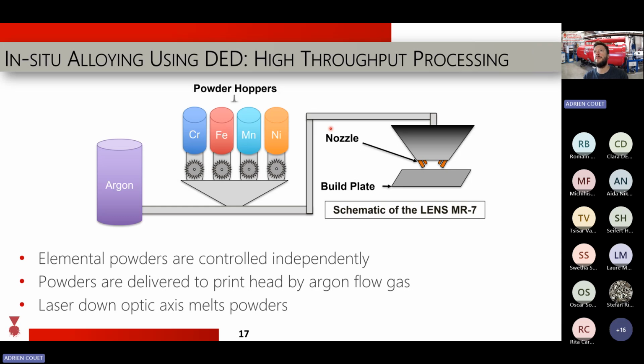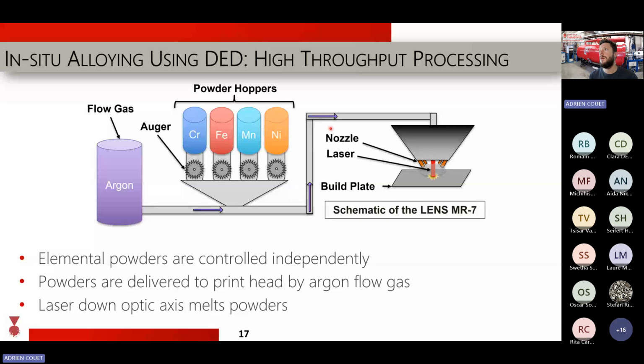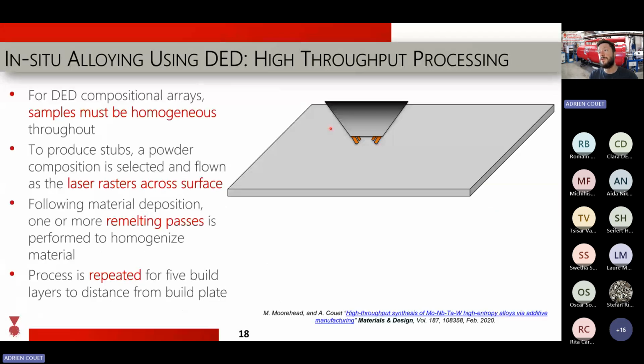And here is an example of how that works. We use those powder hoppers. We flow the powders in our system, and we flow argon to carry the powder of a given composition. And then we blow the powder with nozzles into the focal point of a laser. The part then melts, right? And then we move the focal point for the parts to solidify, and we can melt above it, right? So we create this kind of part on a build plate. That works quite nicely, as you probably know. I mean, additive manufacturing is now a common thing out there.